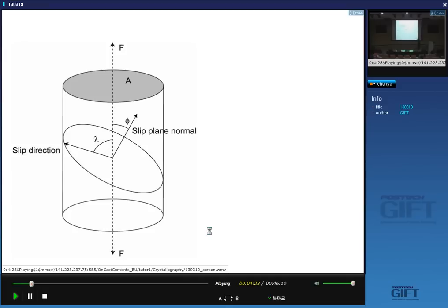When I apply a stress to this crystal, there will be many possible orientations of the slip plane and slip direction. For the {111} family, we have four different possibilities: (111), (-111), (1-11), and (11-1). And within those planes there are slip directions. Taking all that together, there are 12 possible combinations of slip plane and slip direction. So when I apply a stress, I need to know which slip system — that combination of slip plane and slip direction — will operate.